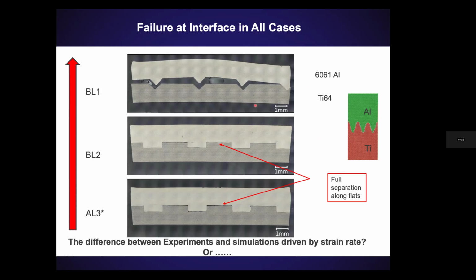But the thing that was driving me nuts, at least, was, well, what's going on? I don't understand why we're not matching our simulations. Because in our simulations, we had titanium and aluminum. The shock was coming from titanium into aluminum, same with the experiment. So why could the difference be there? There are multiple things that could be going on. And when I say difference, I just mean qualitative difference. I wanted molecular dynamics to at least show failure in the same locations that we were seeing experimentally.